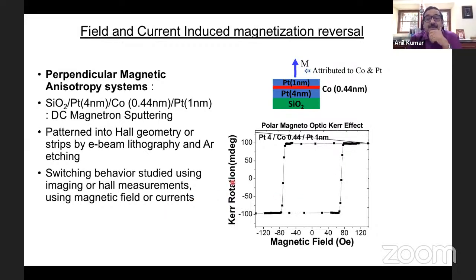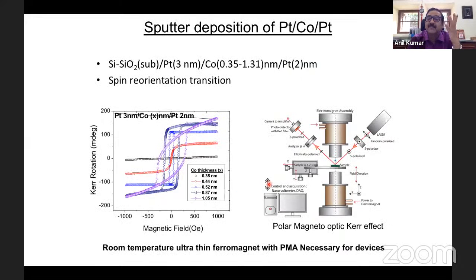You can see here, this is the Kerr rotation. For this structure, when you apply a 120 oersted field, it gets magnetized in the upward direction. And when I bring the field back to 0, the magnetization is almost 100% there. So this is exactly similar to the hysteresis loop I showed you in the beginning. And when I go to the negative side and apply a larger magnetic field, it switches its magnetization down like this, and you get this hysteresis loop, right? So this is not just like that.